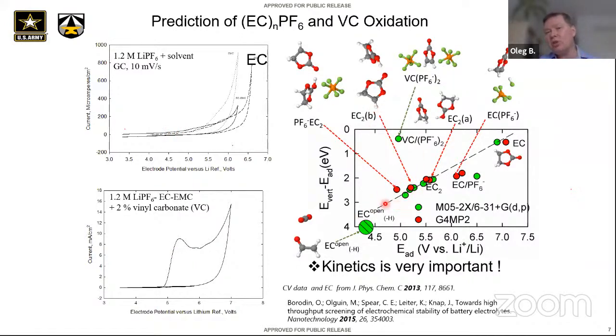So that gets me a more or less unified picture, which says that we need to talk about kinetics and reorganization energy and include it in a screening of electrolytes, even on non-active electrodes. And non-active is actually important because if you think from the perspective of carbon additives, they're very small weight-wise, but surface-area-wise, they're pretty large. So there is a lot of surface. And if oxidation occurs on those conductive additive surfaces, which it might not stick well to, then we keep on oxidizing and decomposing electrolyte, and it's even much worse than passivation of the active electrodes.